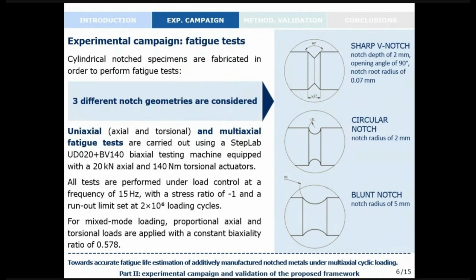So, uniaxial, both axial and torsional, and multiaxial fatigue tests are carried out under load control at a frequency of 15 Hz with a stress ratio of -1. And for mixed mode loading, proportional axial and torsional loads are applied with a constant biaxiality ratio.